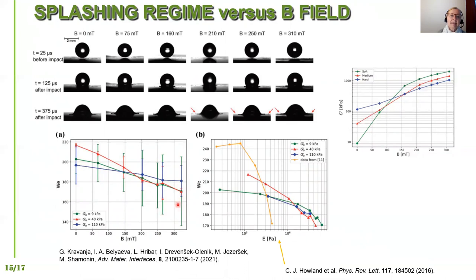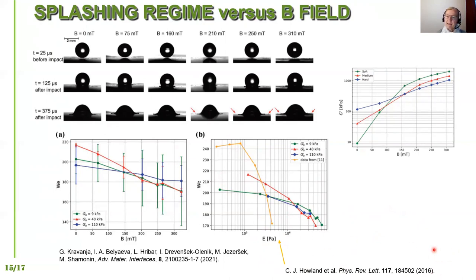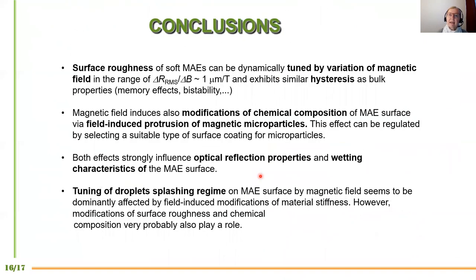By plotting the critical Weber number as a function of the Young's modulus of the material — which we know is modified by the magnetic field — we can see that by increasing the Young's modulus through applied magnetic field, we can tune the droplet splashing characteristics. We can achieve this with one and the same material, whereas a group from the University of Oxford, which published similar research some years ago, used several different materials with different compositions to observe a similar effect.